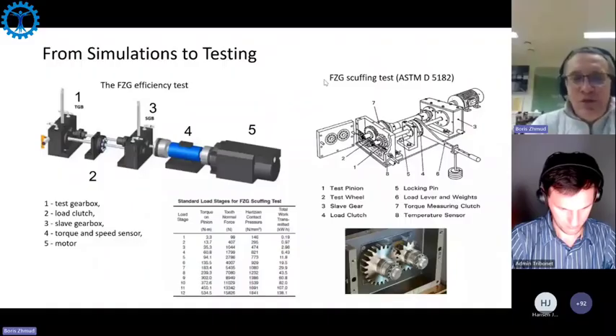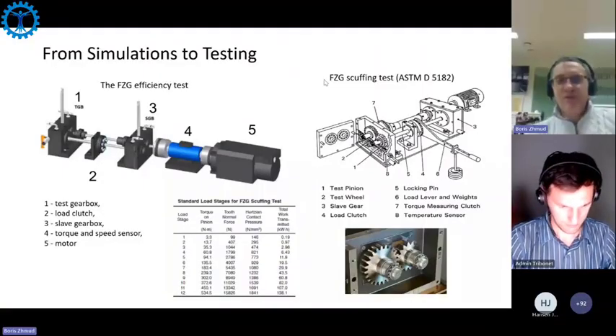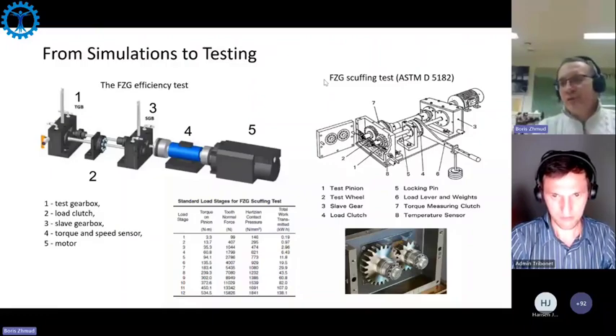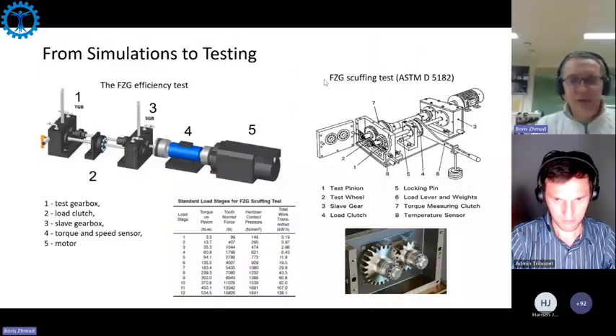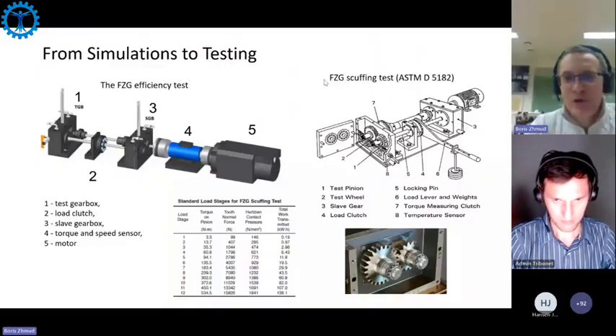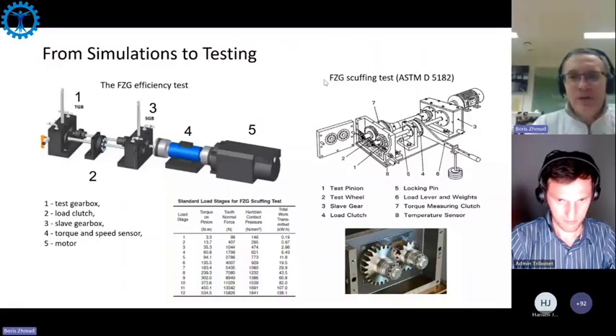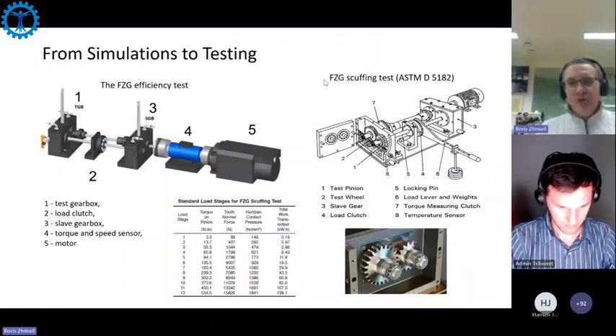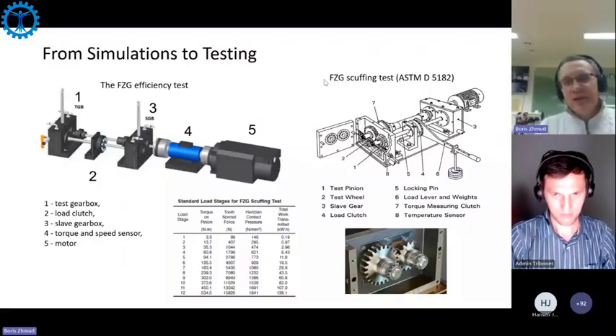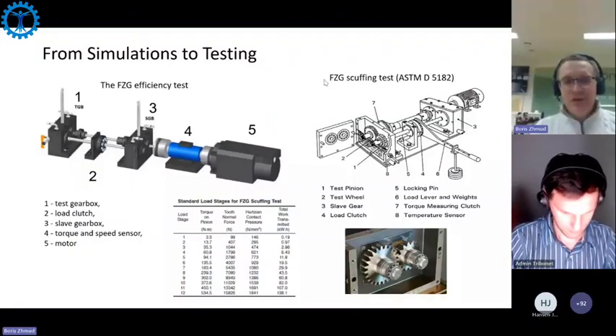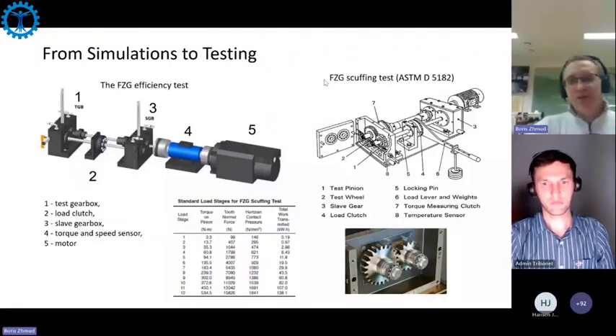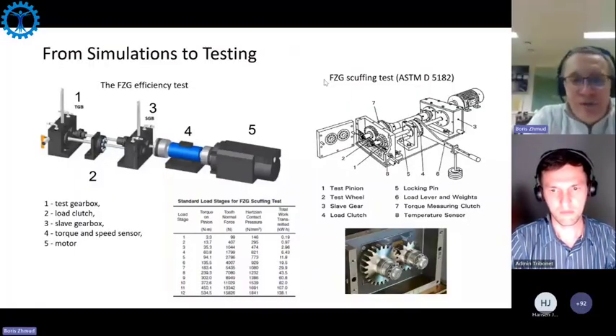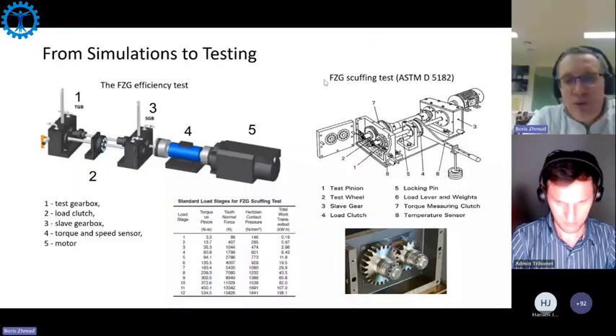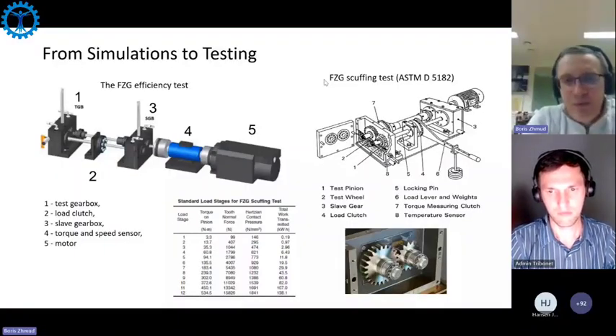We also, as I said, use more advanced rig tests like FZG tests to look on scuffing resistance, because you always try to downsize components, but you cannot downsize them up to infinity. I mean, so electric motor is already very small, but if you go, for example, gearbox and you want to make it light, you would go for smaller gears, but smaller gears will always be loaded more, and when it's loaded more, it at some point will suffer scuffing. And when scuffing occurs, you're no longer concerned about efficiency because you have a much bigger problem to address.